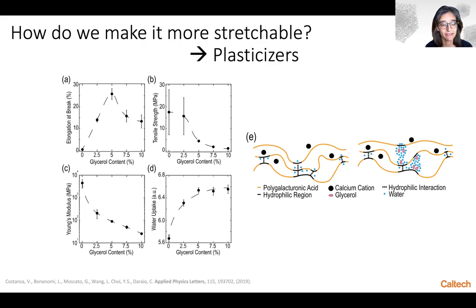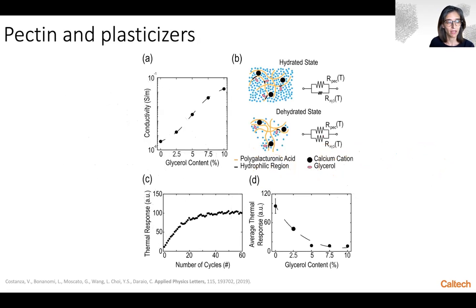But they come at a significant cost to the responsivity, related to the increased water uptake due to the hydrophilic interaction between glycerol and water. Pectin as plasticizers effectively increases the amount of water, shorting the circuit.